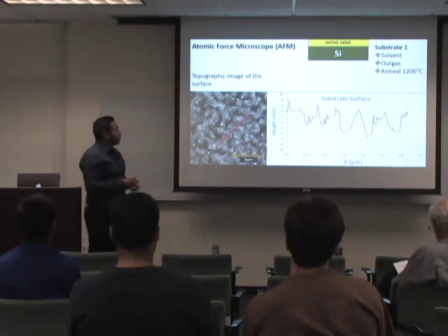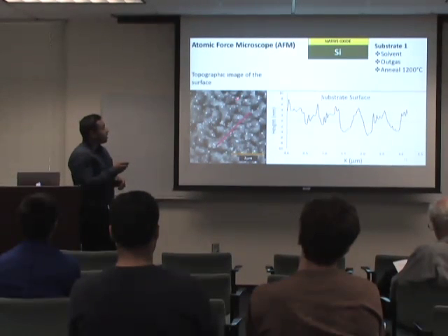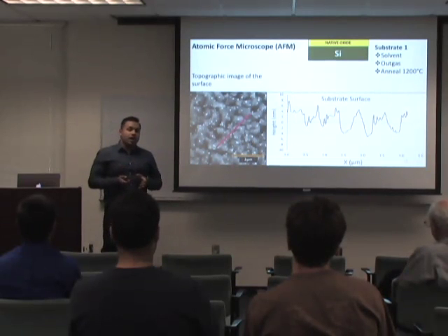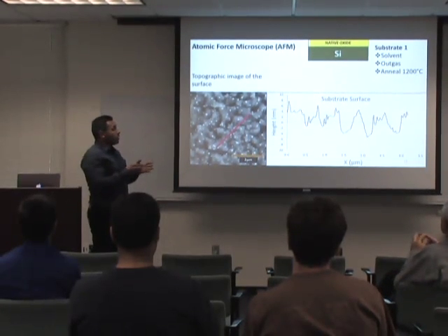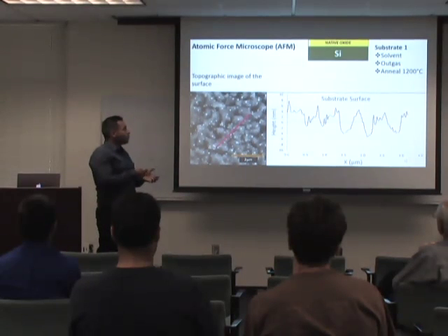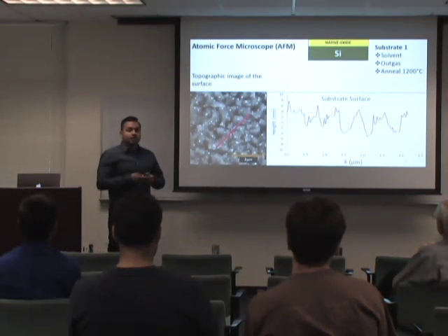Also, we think that these white spots are silicon carbide. Instead of removing all the carbon, when the silicon was hot, the carbon was reacting with the silicon, and we have some silicon carbide. That's what we think.